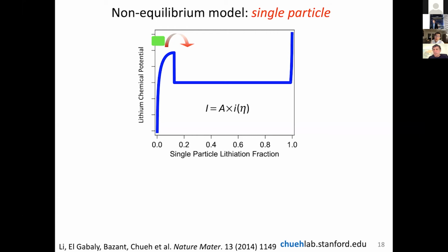So in order to pump lithium into the system, you have to apply an overpotential that is slightly higher than the blue. You will notice that there's a hump and a drop. That is the nucleation barrier. But because there's only one particle in the system, we only have to have nucleation happen once. So once we nucleate the new phase, so remember lithium iron phosphate has a very large miscibility gap, then the phase transition commences and the intercalation can continue. So essentially, this red dashed line represents the actual chemical potential, and the difference between the red line and the blue line is the driving force.